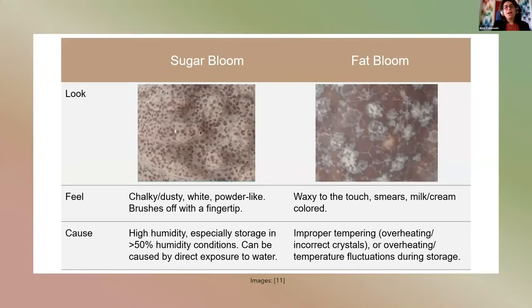So, bloom. There are two types of bloom. Generally, there's sugar bloom and fat bloom. Sugar bloom has a chalky, dusty, powder-like feel to it. It's usually a little bit whiter than fat bloom, and it can brush off with a fingertip. It won't completely come off, but you can see it start to brush off when you rub it. It's caused by high humidity. If you're storing chocolate or casting chocolate in greater than 50% humidity, especially higher, like 70 plus, this can cause sugar bloom.